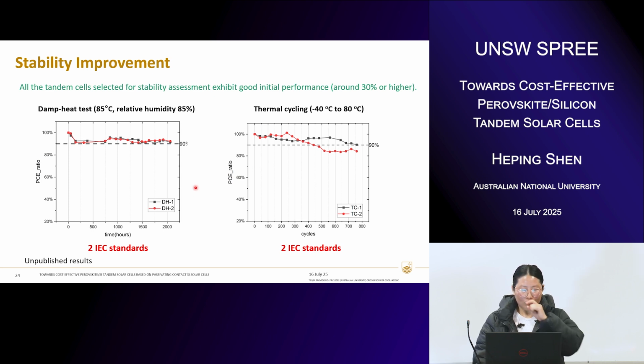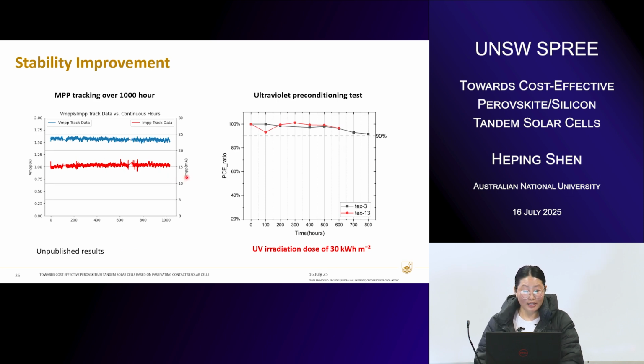For example, our tandem cells, these highly efficient cells, can pass the IEC standards for damp heat, and can pass the IEC standards for thermal cycling. They also show quite good stability, very negligible performance loss, probably less than 2% on MPP tracking under light. And the UV exposure doesn't give them too much degradation. So these are very recent results. We haven't published yet, but they give us much confidence in terms of further improvement of the perovskite silicon tandem solar cells.